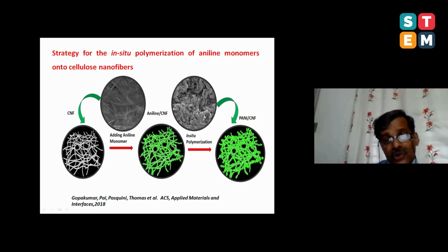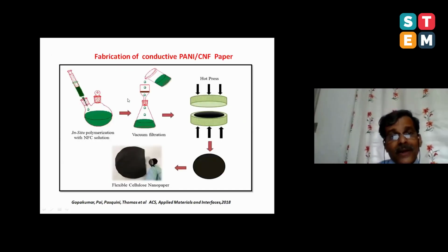Look at the microscopy picture of the internal structure of this paper. This is nanocellulose paper. This is in situ polymerized aniline nanocellulose paper. And I wanted to show you, this is our fabrication setup, a very simple setup. We made nanocellulose suspension from waste. We injected aniline with a catalyst and polymerized it. Then we did a vacuum filtration process. We made beautiful paper, and this is hot pressed. Look at this flexible paper Dibu has made.